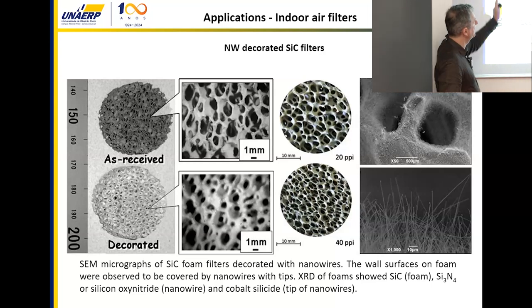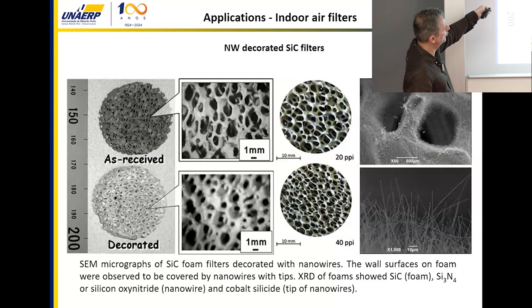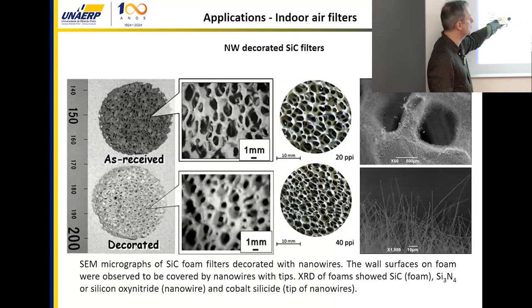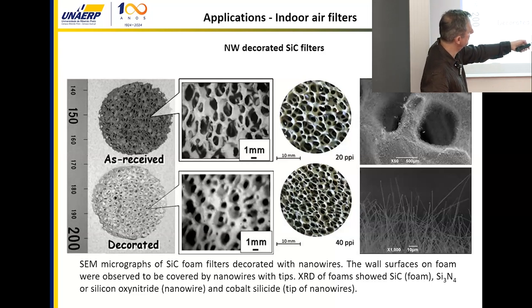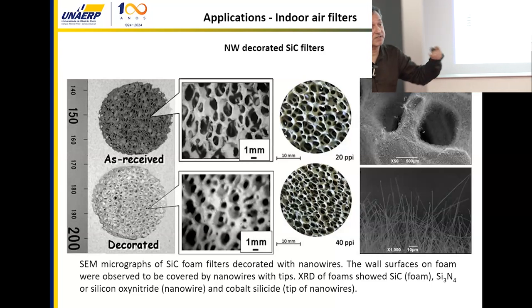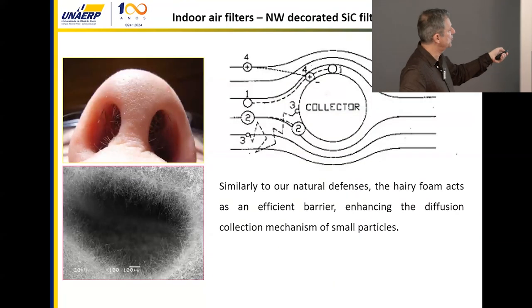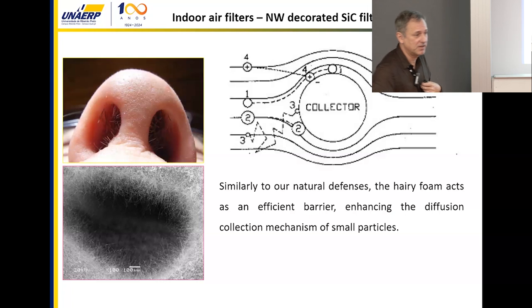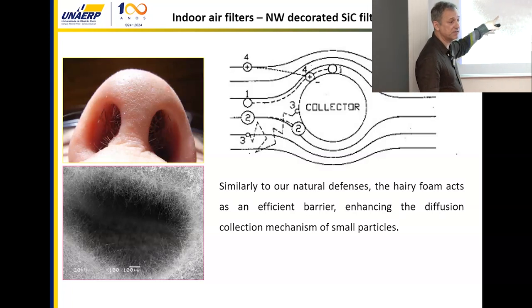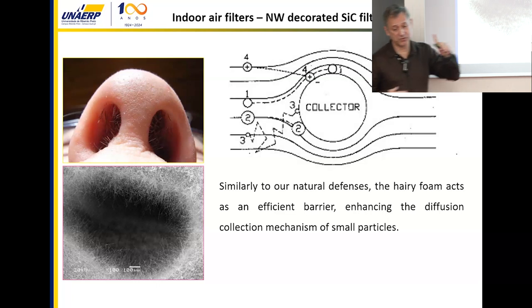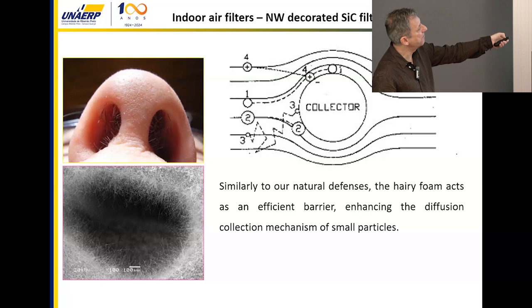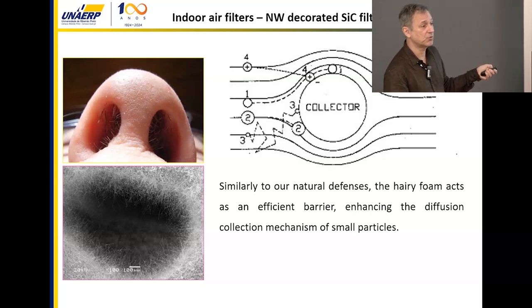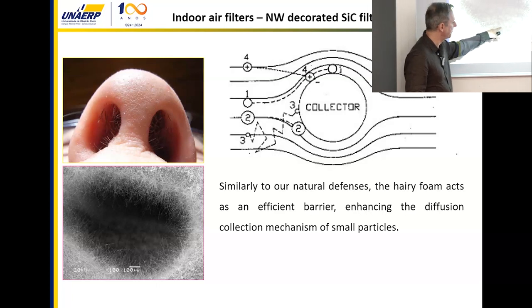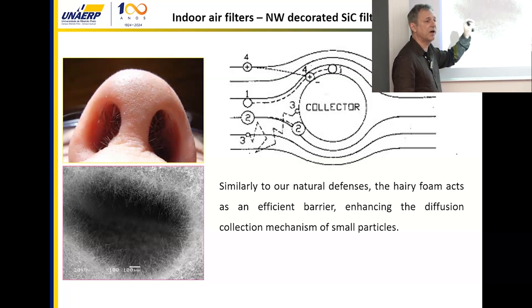In this case, we used the ceramic foam, 20 ppi and 40 ppi, and just put these nanowires on the surface of the struts. So you see here the nanowires covering. And what was the idea? The idea was to simulate our defenses. So in this case, you have a lot of nanowires. The idea is that the nanowire helps the diffusion mechanism to collect particles. So the smaller the filament here, the smaller are the particles that you are going to collect.